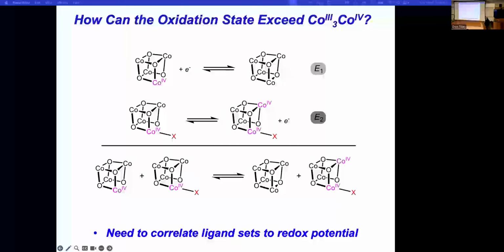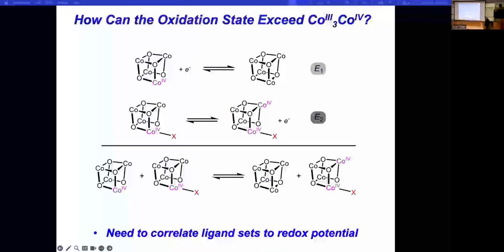So with that information in hand, the next thing we wanted to do is try to deconvolute the redox behaviors of different cubanes, because it looked like with the redox disproportionation, what we're seeing is just different energies or different oxidations depending on the ligand sphere around the cubane. So that is indicated here, and how those two half reactions would come together to give effect and effect electron transfer. Now here I write the two-hole product is two cobalt fours, but I'll get back to that later in the talk.